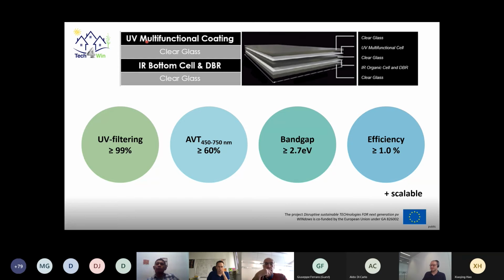So one of the targets we have that you can see here on the left in the circle is UV filtering more than 99%. Next to that, of course, the visible and the infrared spectrum parts should reach the bottom cell. So we're also looking at that, and it should be as transparent as possible. So we're aiming for an average visible transmittance above 60% for our top cell, which means that we're having a quite difficult band gap target as well. We're aiming for a band gap of at least 2.7 electron volts, so that we absorb the UV part before 450 nanometer. That's what the aim was at the start of TECH4WIN.